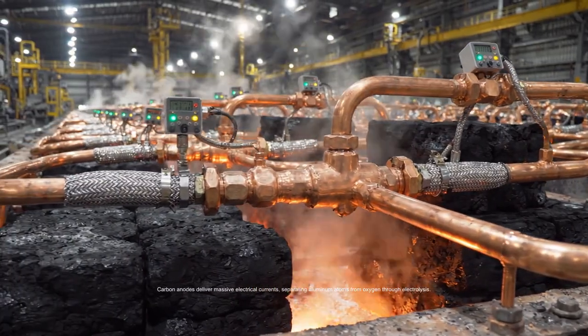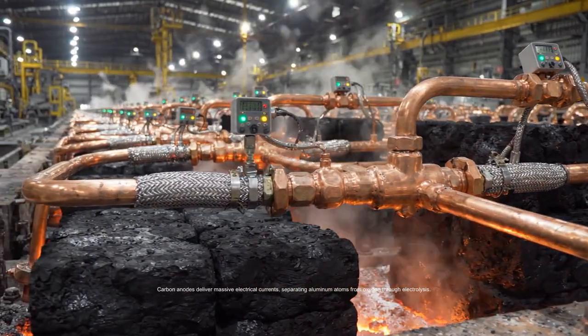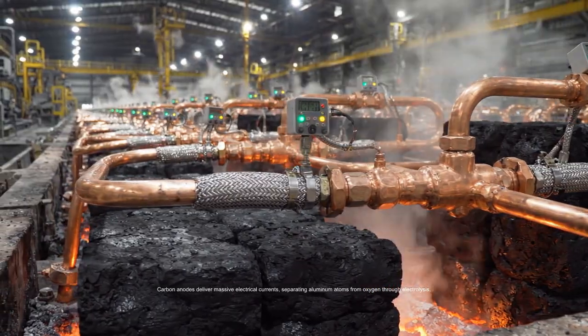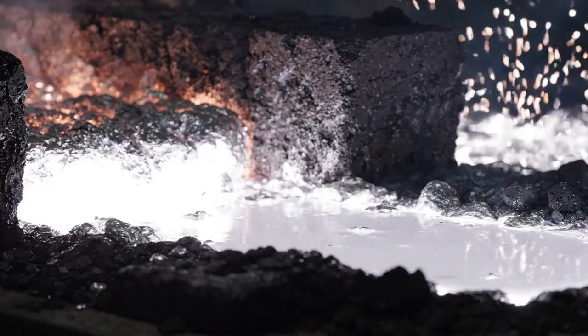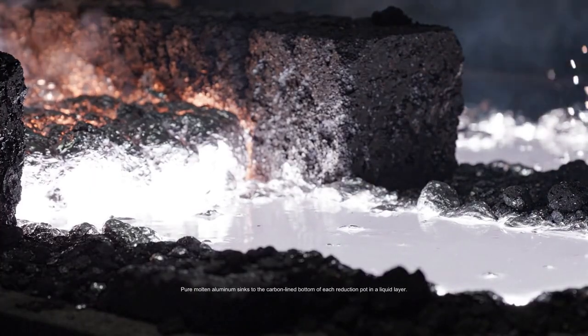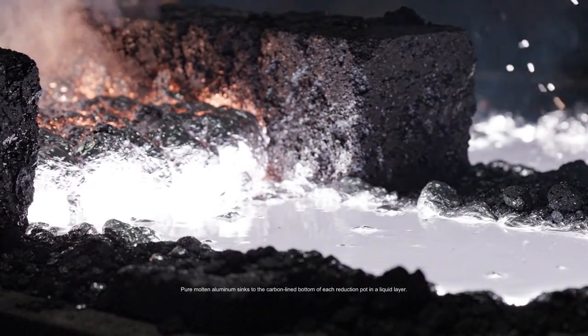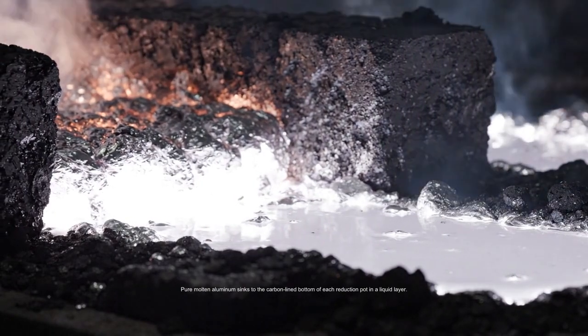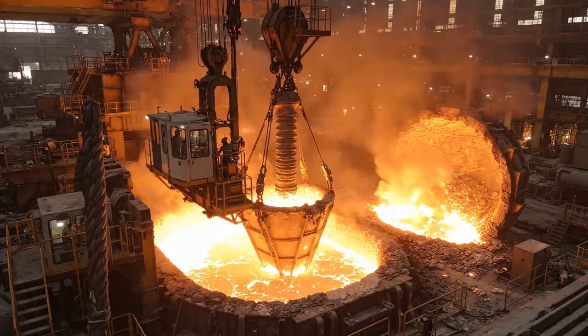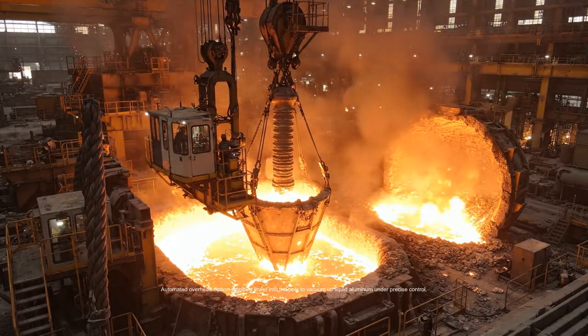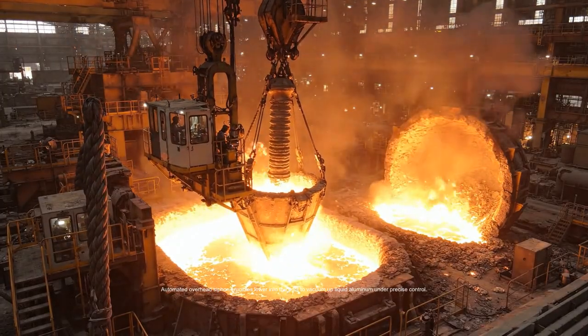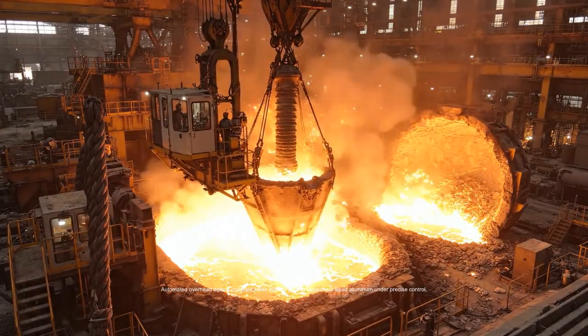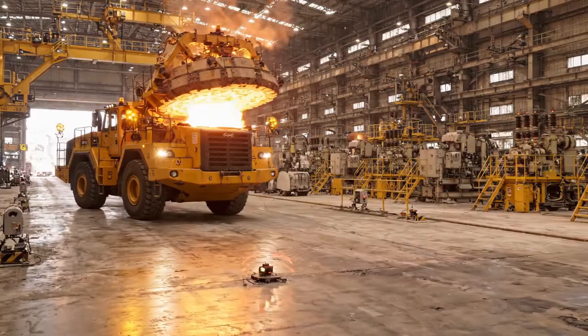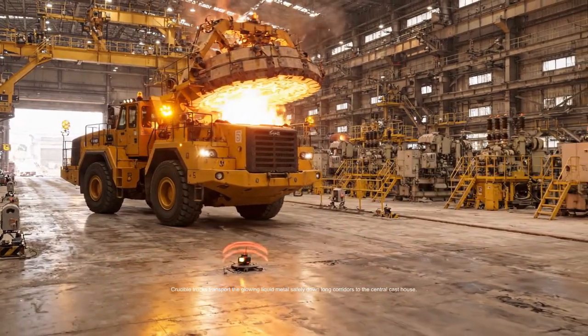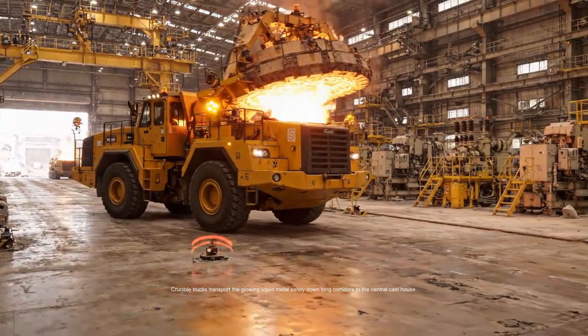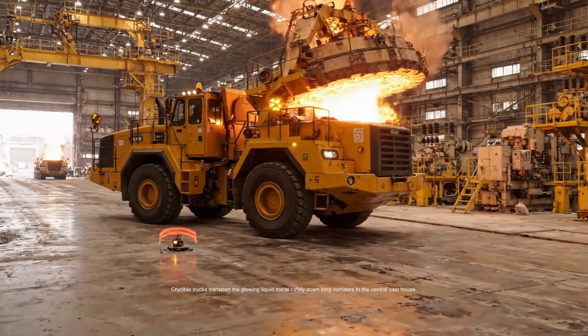Carbon anodes deliver massive electrical currents, separating aluminum atoms from oxygen through electrolysis. Pure molten aluminum sinks to the carbon-lined bottom of each reduction pot in a liquid layer. Automated overhead siphon crucibles lower into the pots to vacuum up liquid aluminum under precise control. Crucible trucks transport the glowing liquid metal safely down long corridors to the central cast house.